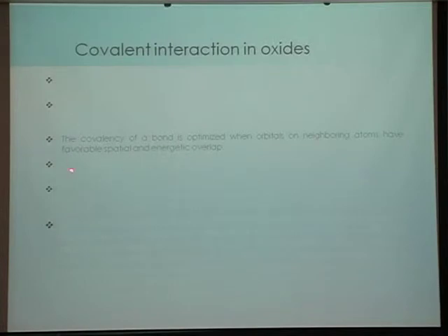Now, covalency of a bond is optimized when orbitals on neighboring atoms, in this case metal and oxygen, have favorable spatial and energetic overlap. This is mandatory. This has to happen. Because of this, in the case of oxygen, the only orbitals that we talk about are the oxygen 2p orbitals. These are the only ones which have these favorable conditions to undergo a covalent interaction. The other 1s and 2s orbitals you can forget about mostly. That's because of this overlapping problem.